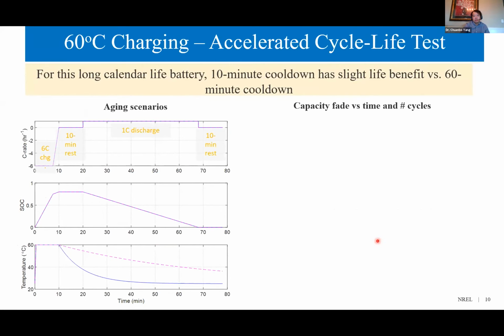Besides improvement of charging acceptance and lithium plating, elevated temperature will significantly impact battery life also. This is addressed by a physics-based surrogate life model of a high quality, long calendar life commercial NMC graphite cell, used to analyze life benefits and detriments at high temperature fast charging. This commercial cell has a very good calendar life, and for this study we consider the cathode cracking mechanism and Arrhenius temperature dependence. We didn't address the lithium plating mechanism.